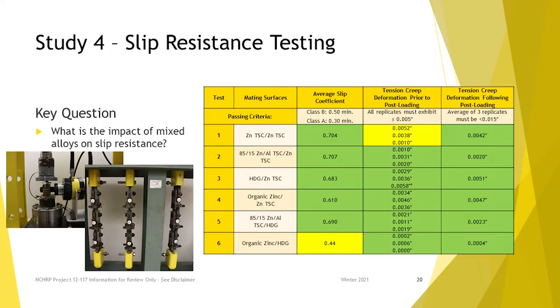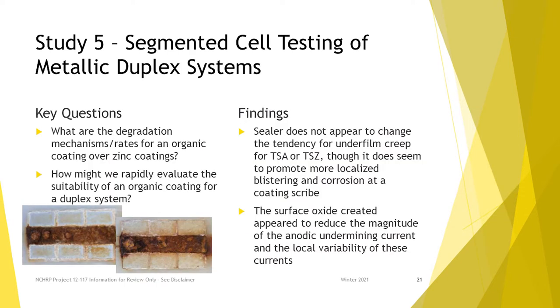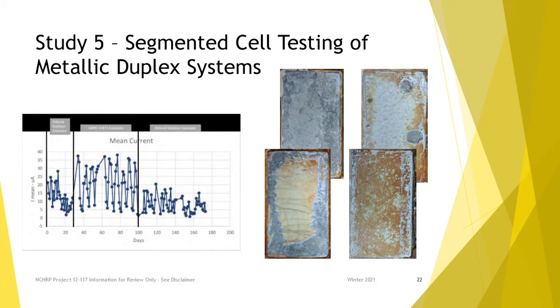The data showed that for the most part these combinations of materials can meet the Class B slip requirements. The last study looked at the mechanisms of duplex system failure — you've got a paint protecting zinc, and the zinc protecting the steel. When a paint fails, the zinc is basically a barrier coating; there's no sacrificial protection going on until you expose steel. Once you expose steel, you get the sacrificial benefits. We did a detailed analysis of what goes on at those defects and how large they have to be. All that detail will be in the technical report.